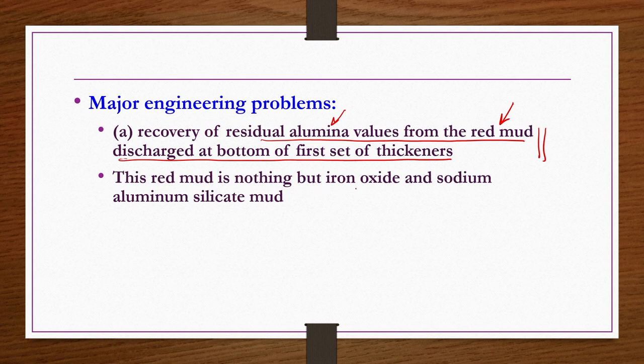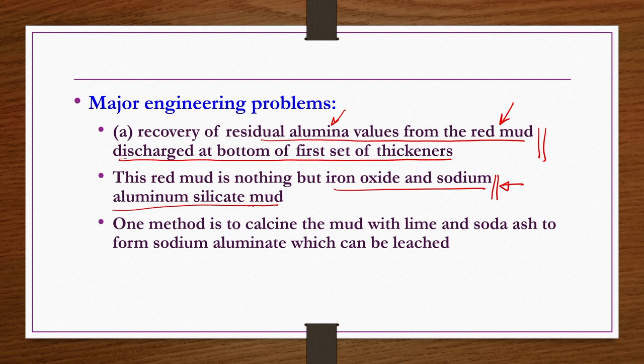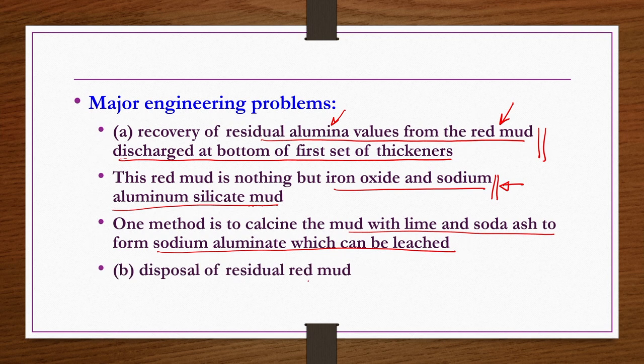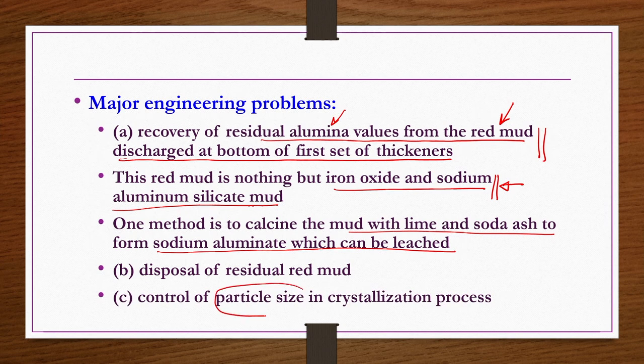This red mud is nothing but iron oxide and sodium aluminum silicate mud. So obviously because of their contents, you have to recover them. Not only recovering, but discharging the red mud after recovering the alumina is also an issue. One method is to calcine the mud with lime and soda ash to form sodium aluminate, which can be leached. And then another problem is the disposal of residual red mud. Further, control of particle size in the crystallization process is another issue that one should be careful about. So that is what we have seen.